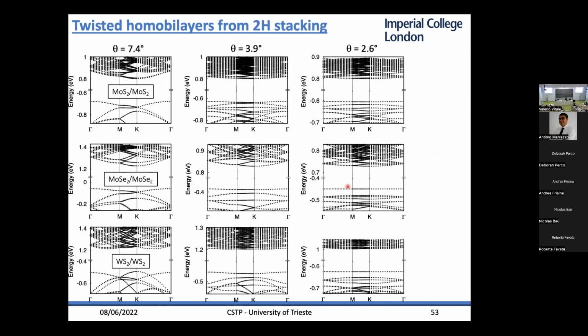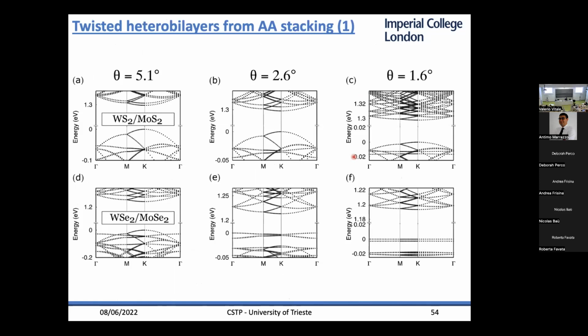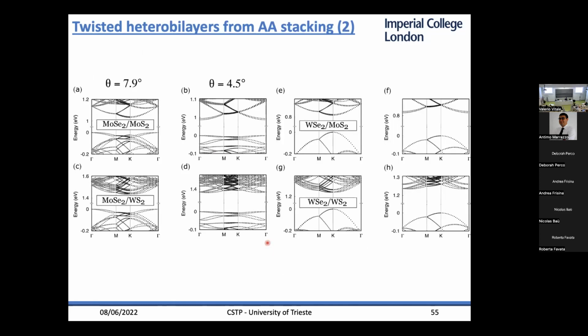You can play a similar game if you start instead from AA or 2H. In this case, the 2H stacked systems have a different band structure at the top of the valence band. Now you have a single very flat band already at 2.6 degrees. So by changing the original stacking and then twisting, you can get a very different band structure. Then you can play with hetero bilayers, and in hetero bilayers, as you can see, sometimes you get these K valley bands on top instead of gamma. So you can really have quite a range of different bands at the Fermi level, which come from gamma or K valley.